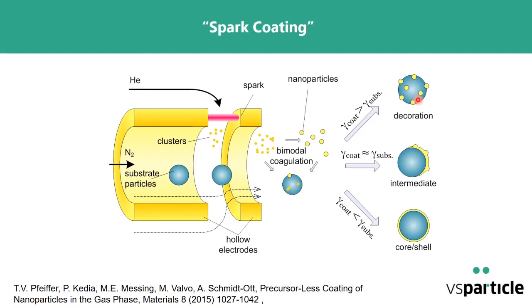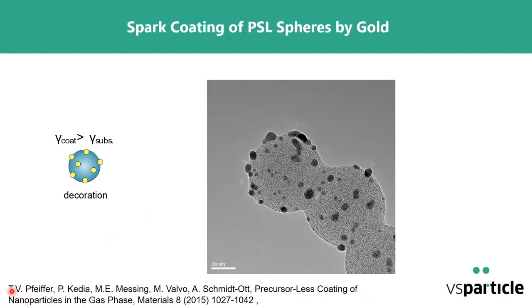We did this, this was mainly the work of Tobias Pfeiffer, who is now the CTO of VS Particle, for a polymer. These were PSL spheres. These were the particles, and of course, it's a polymer, so they are heat sensitive. And so we make use here of the fact that the vapor meets these particles at a temperature which is already near room temperature. And you see on the micrograph that they look very nice.